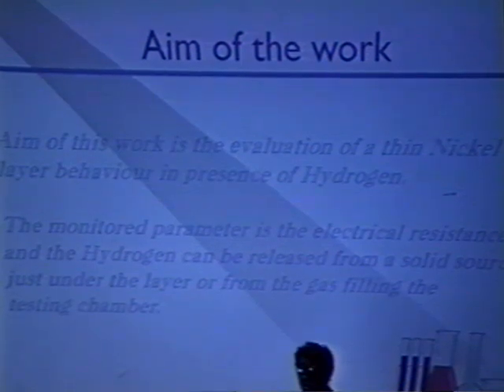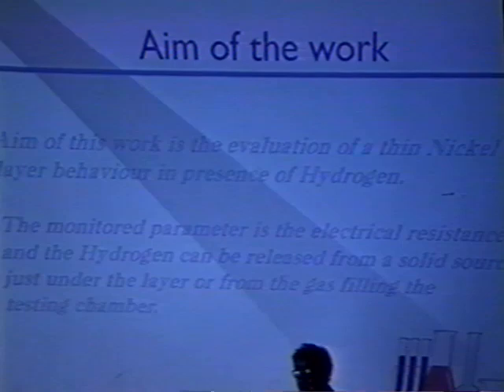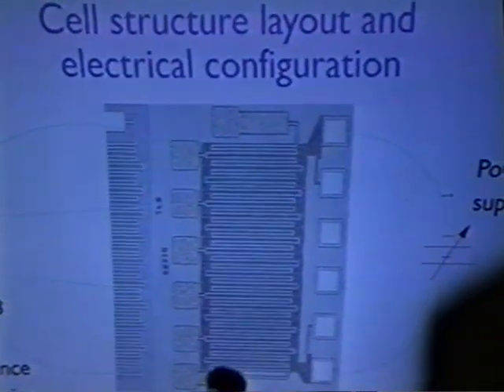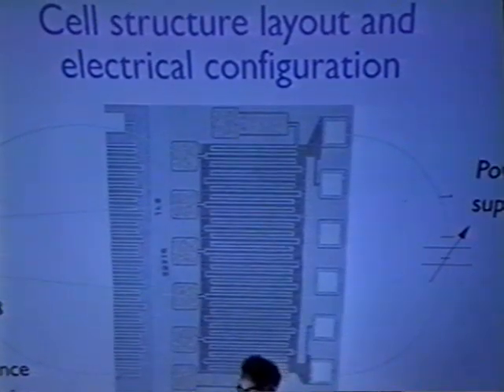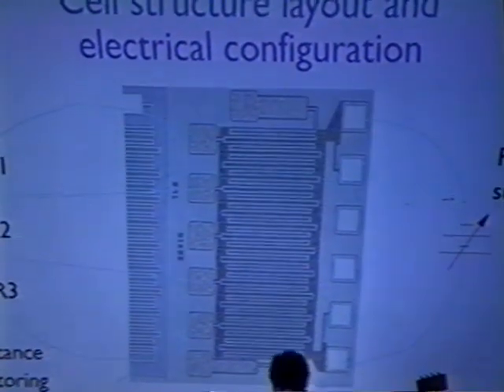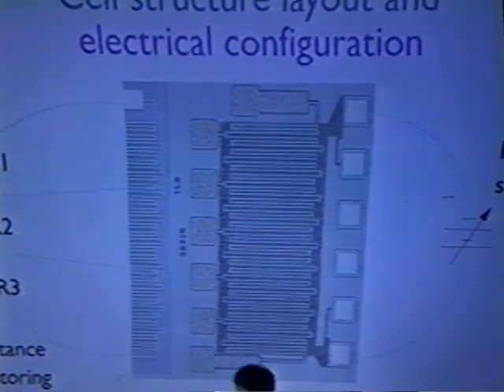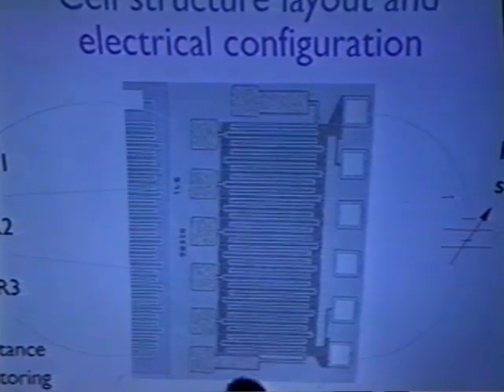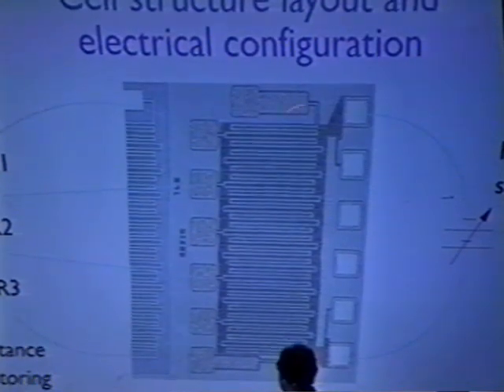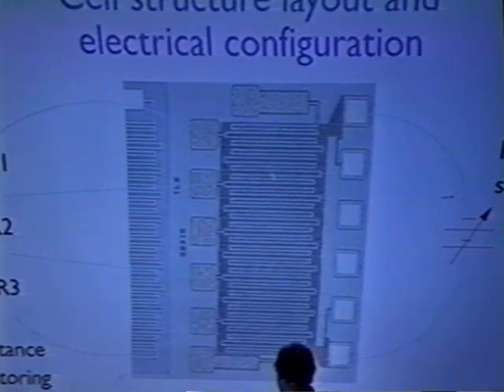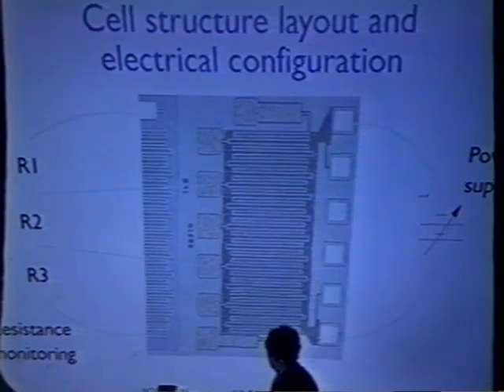For doing that, I would like to use special solid films with high content of hydrogen that are commonly used in the microelectronics industry. Also the behavior of that layers is well known. This is the layout of the cell. I showed in my previous presentation the real dimension of the cell, it is very small, as you can see. Here you can see the snake that is the nickel layer, the white one. The brown one is just the heater, just below the hydrogen content layer.